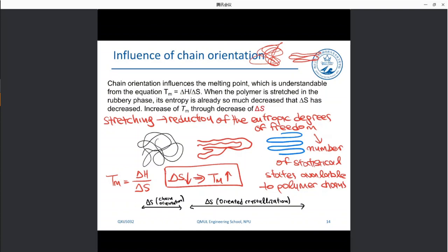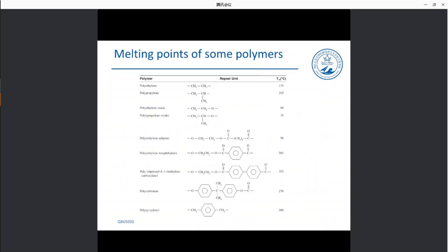That is very important in the case of elastomers, as we will see, which are fully amorphous materials. Because we're stretching and orienting these materials, we create crystallites in there. So we create a kind of composite, let's say, a semi-crystalline material, even though we were starting from an elastomer. And you will see that it displays unique stress-strain curves, which are not what is expected from the theory, okay? That is very interesting and important. We will see that in the relevant part of this course on elastomeric materials, okay?